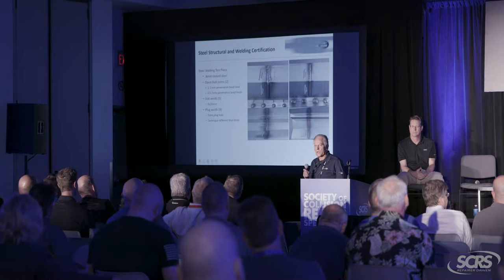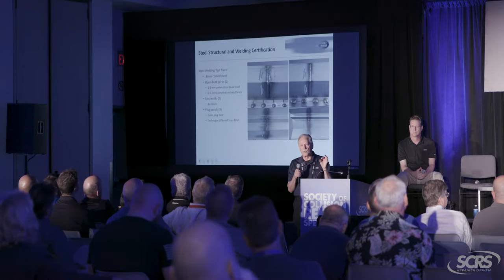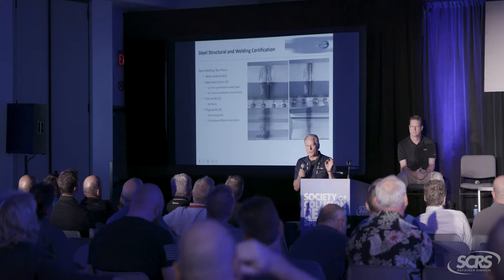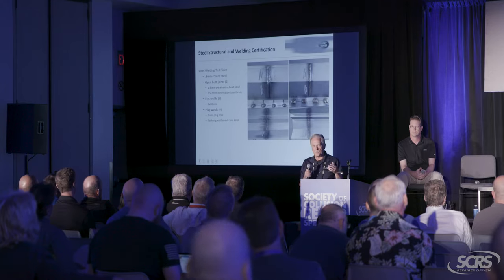The plug welds that they're tested on have only a 5 millimeter hole, which guys are not quite used to. Some people are still thinking like, well, every time we do a plug weld, it's 8 millimeters. But Jaguar Land Rover, like a lot of the other OEMs, on a lot of panels, on the thinner panels, they're using smaller holes.